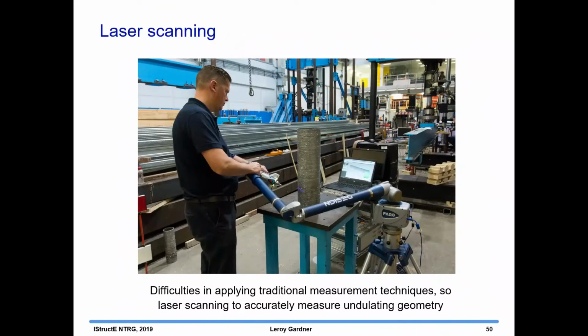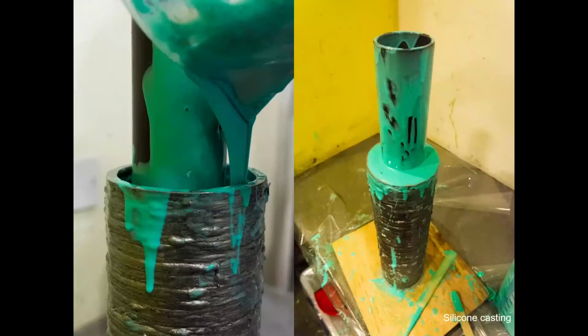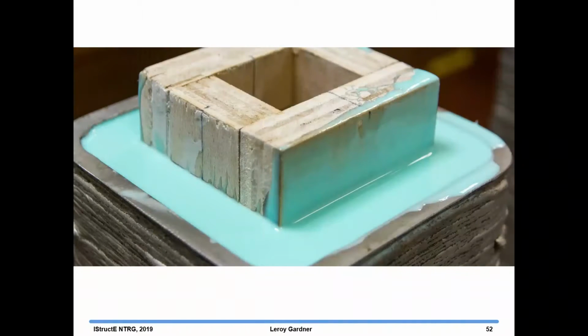Because of the geometric variation, it's not so easy to get an accurate measure of the real geometry of these things. So you can't just do normal geometric measurements using calipers and so on. So we used 3D laser scanning in order to capture the geometric profile. Now, unfortunately, most of the bridge is tubular, and it's not so easy to scan the inside of tubes. So we scanned the outside, and then we created molds of the inside by pouring in silicone, letting it set, and then pulling it out.